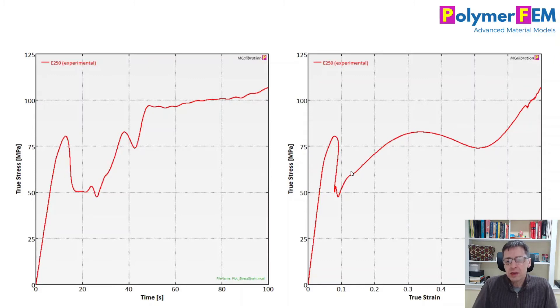perhaps that's related to the strain rate. Because once the neck goes through that center element, the strain rate goes quickly up. So the material model is strain rate sensitive. So the stress will be higher at higher strain rates. So perhaps this is related to that strain rate dependence. And this drop is because once the neck has gone through the center element, the strain rate will actually be very low because the neck will go somewhere else. But it's an interesting curve, a bit surprising at first that this is what happened.